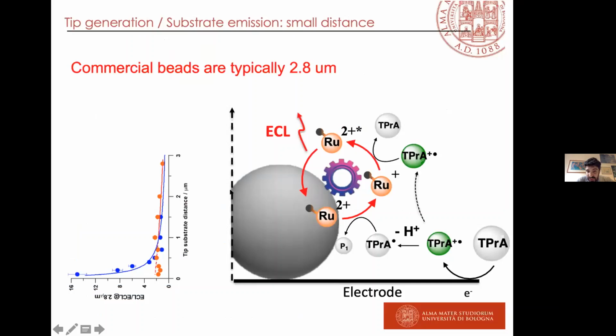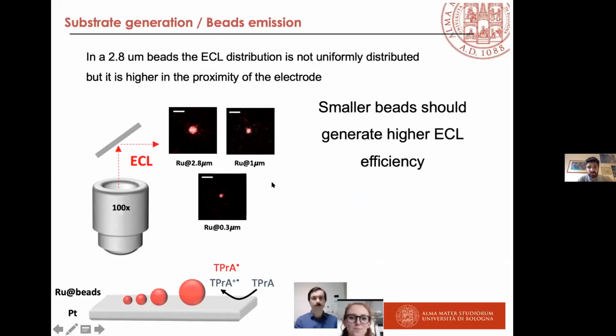In fact, if you take the Roche system, so if you take Elecsys, typically they use 2.8 micrometer beads, so bigger beads with 2.8 micrometers as a diameter. And if we go to a smaller diameter, we can concentrate the amount of ruthenium dye for our catalytic cycle in the area where the ECL mechanism is more active, where we have this exponential trend. And that's what we did.